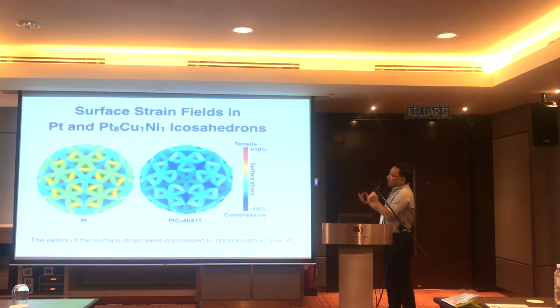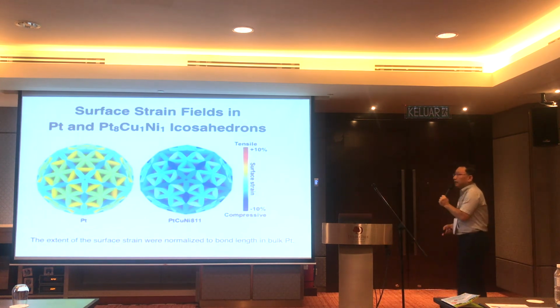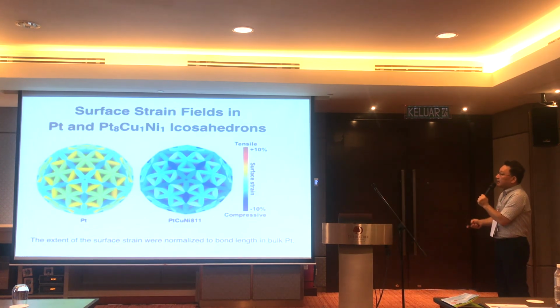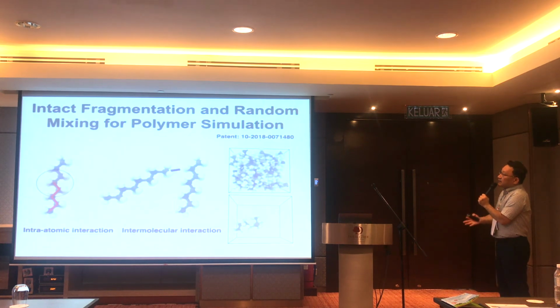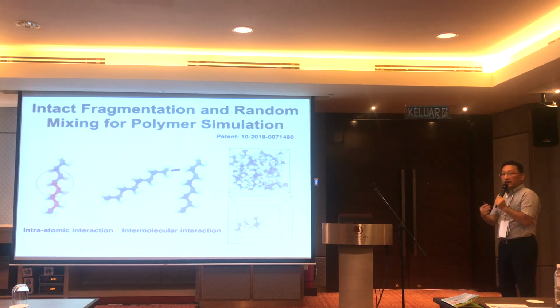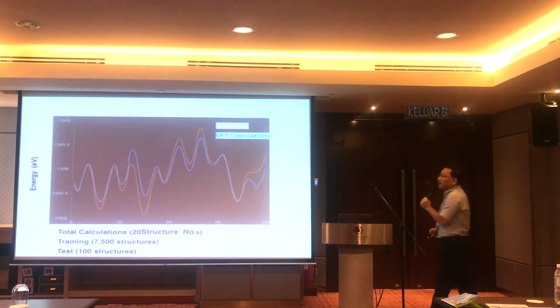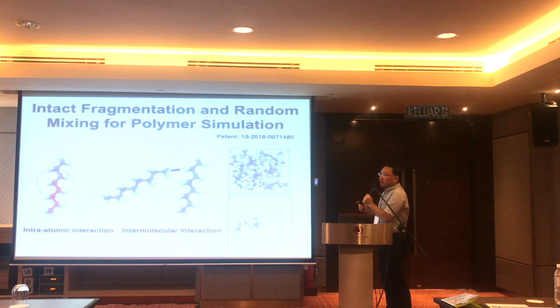This is the surface strain field on the nanoparticles. We found that platinum on the surface is under compressive strain. Compressive strain is good for oxygen reduction reaction catalyst materials. Recently, I'm also working on polymers. Can you predict polymer structure? Polymer is more difficult than crystalline because polymer can fold. They can change the topology by themselves. So it's much more difficult than crystalline.